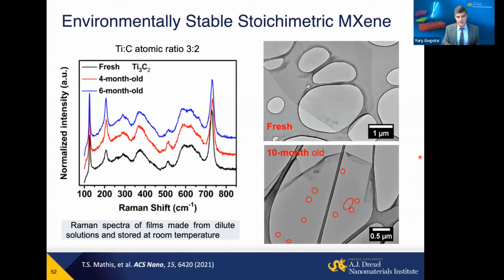Look at them as carbides and nitrides of transition metals. You have strongly bonded metallic atoms. So in terms of mobility, they're better than metal. Say, the breakdown current for monolayer MXene is about 2 orders of magnitude higher compared to copper, and at the same level as graphene. So the atoms are sitting stronger. If you irradiate them, you can kick atoms out of the structure, but MAX phases, their precursors, are considered and explored in materials for nuclear safety because they don't really swell much. So I guess they will be sufficiently resistant, but it's outside my personal field of expertise, and I don't think much has been done on exploring those properties of MXene.